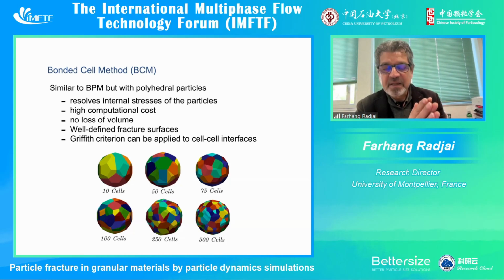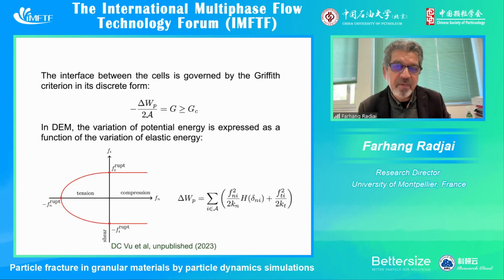And when we use these interfaces between particles, we have to apply the fracture mechanics rules. So here we have no loss of volume. The volume is conserved. We get generally well-defined fracture surfaces. And as I told you, we apply the Griffith criterion to cell-cell interfaces. So typically, when we apply the Griffith criterion, we have to use it in a discrete form. So we assume that we have a toughness of the material, which is G here, and we use the same rule based on energy, so the potential energy, and A is the surface area between two particles.